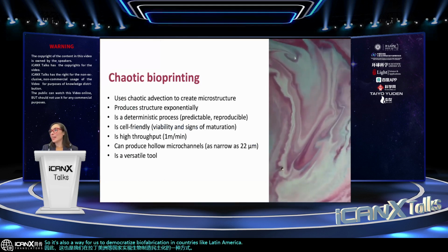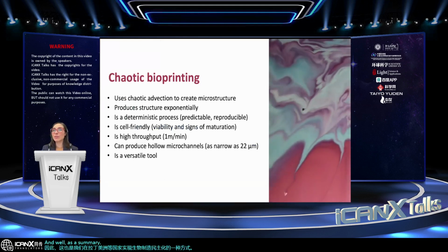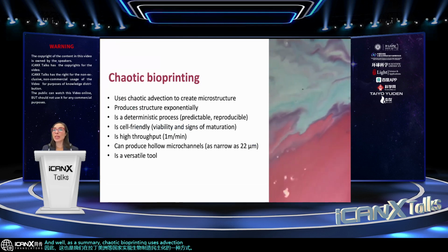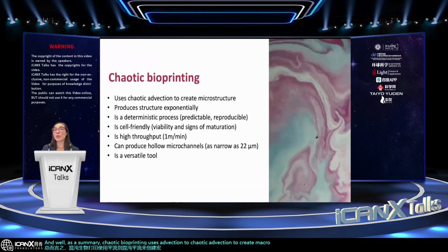And well, as a summary, chaotic bioprinting uses chaotic advection to create microstructure. It produces the structure exponentially, is a deterministic process, therefore it's predictable and reproducible. It's cell-friendly because we saw not only viability of our cells, but also signs of maturation towards the formation of skeletal muscle tissue. It's high throughput. We can literally print 1 meter of these structured hydrogels in only 1 minute, and we can produce hollow channels as narrow as a blood capillary, and it's a versatile tool.